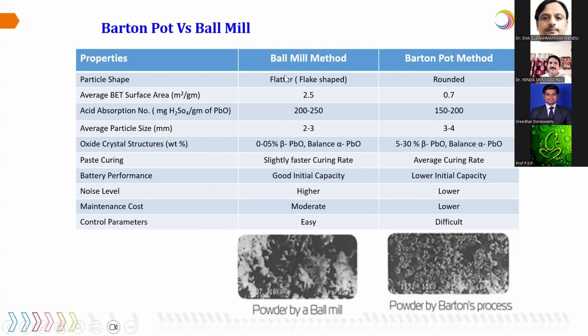Okay, right. So if you see here, in the ball mill method the particle size is around, sorry, this is my mistake, this is not mm, this is microns. The average particle size is 2 to 3 microns, and for the Barton pot it is around 3 to 4 microns. As we know, a higher particle size will have a lower surface area, and a lower particle size will have a higher surface area. Mostly in the whole world there are these two processes, and they are used according to the application. For stationary applications, the Barton pot method is used, and for automotive and quick charge, quick discharge applications, we use the ball mill technique.